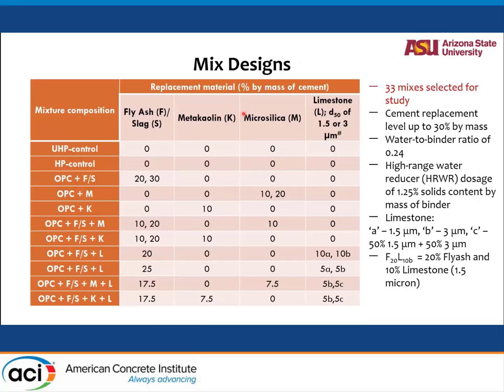So we did about 33 mixes. Here are a few of those mixes and different combinations of fly ash and slag, combinations of metakaolin, microsilica, limestone of different sizes. Water binder ratio was between 0.2 to 0.24, depending on the application, depending on the binder, and depending on the flow that we wanted. But generally, just a set of mixes.